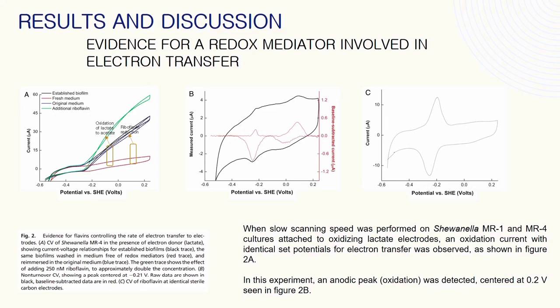When slow scanning speed was performed on Shewanella MR-1 and MR-4 cultures attached to oxidizing lactate electrodes, an oxidation current with identical set potentials for electron transfer was observed, as shown in Figure 2a. When the medium was replaced with fresh media lacking lactate, and incubated for 12 hours to deplete the remaining electron donors, the oxidation current dropped to the background level.